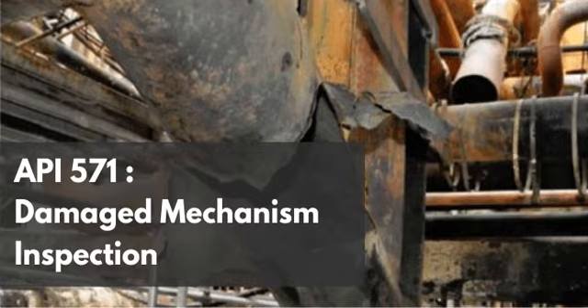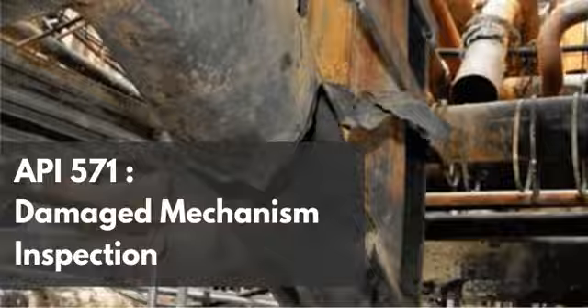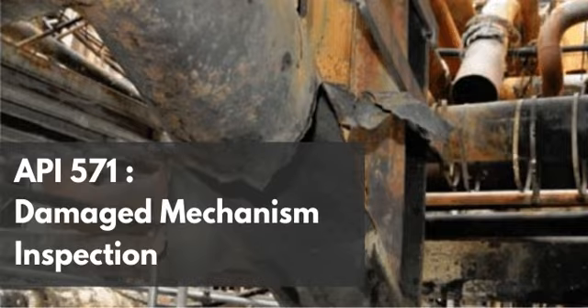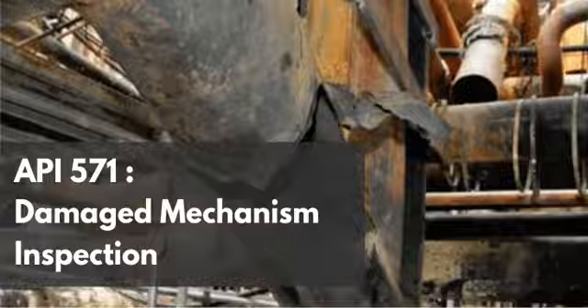Now, what about low alloy steels? How is that family defined, and why are we grouping it with carbon steel when it comes to this corrosion? Well, low alloy steels represent a significant step up in engineering complexity. This is a family of steels containing intentional additions of alloying elements, most notably up to 9% chromium, along with elements like molybdenum. The specific engineering reason we use these in refineries is for high temperature strength and creep resistance. Just to level set for a second, creep is what happens when metal is exposed to high stress at very high temperatures over a long period, right? It literally starts to stretch and deform permanently over time.